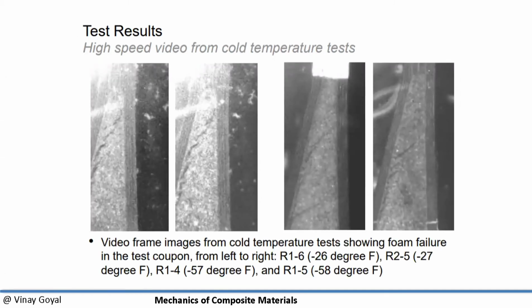Here's a high-speed video for the cold temperature test. You can see here quickly how the crack grows relatively fast, and it shows foam failure in the test coupon from left to right. And you can see here that's for minus 26 degrees F, minus 27 degrees F, minus 57 degrees F, and minus 58 degrees F. So there's a difference in behavior, and you can see that shown by this picture.